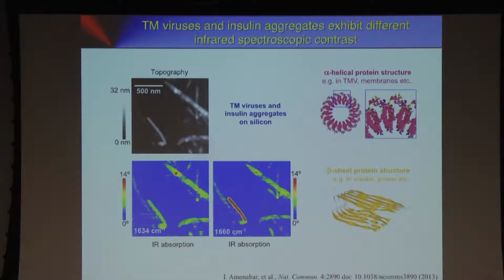And so we just took insulin monomers, heated them a little bit, added some chemicals, and these insulin monomers are known to fibrillarize and form aggregates. We mixed the stuff together and put it on a silicon substrate. Here we have the topography image, with these elongated structures, here's the virus, and here these aggregates. But it's difficult to say without chemical information.